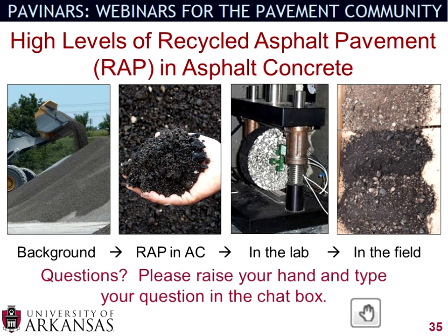When we're talking about percent RAP, we're talking about percent aggregate weight. So if you have 1 ton of aggregate and you're using 20% RAP, that means that you have, oh boy, I shouldn't use 1 ton. That means you have 1,600 pounds of virgin aggregate and you have 400 pounds of RAP. And that 400 pounds of RAP includes both aggregate and the asphalt cement that is on that RAP.